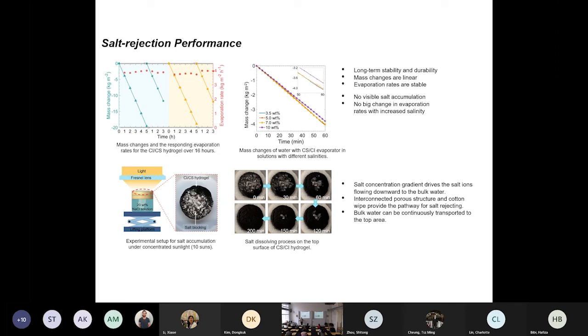The rest of the day, the material itself is still water absorbent. The water keeps absorbing through the micropores, microchannels, and it's going to wash away the salt from all of these pores, down to the bottom, down to the bulk water. That was the concept, and we demonstrated that. So you see, after 2 hours without the solar absorbance, in the dark room, all of the salt has gone back downwards to the bulk water. So we demonstrated this already.